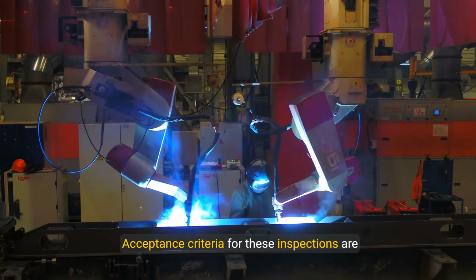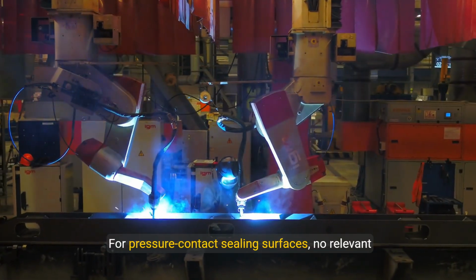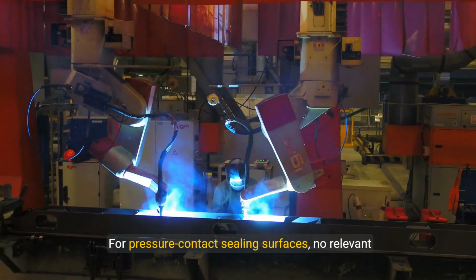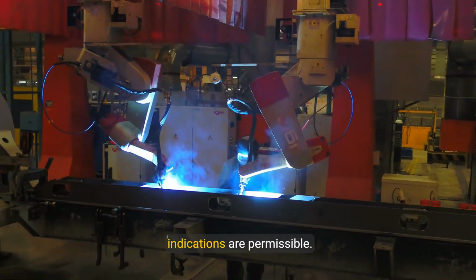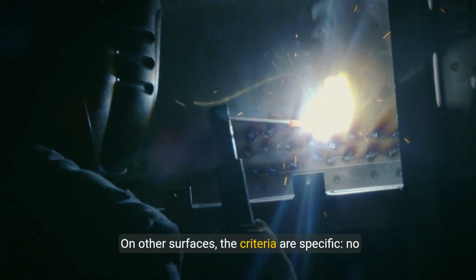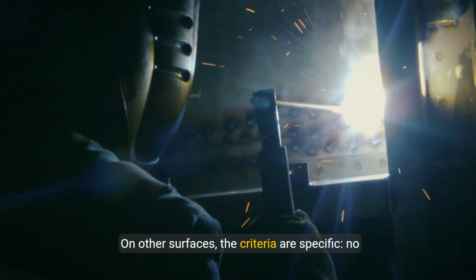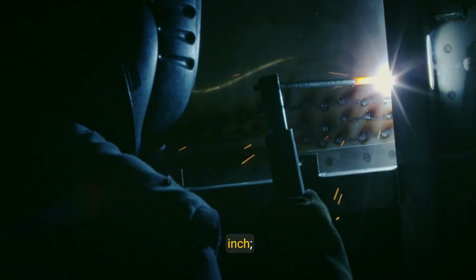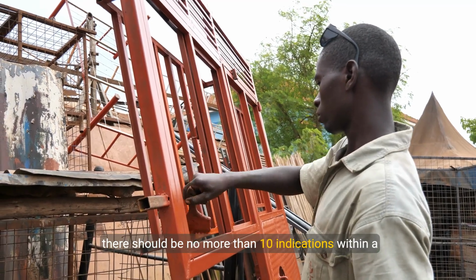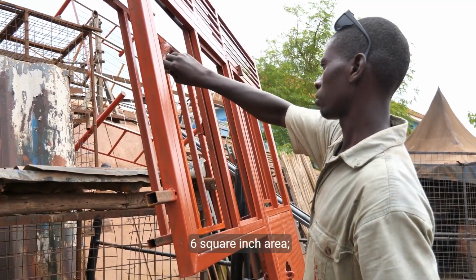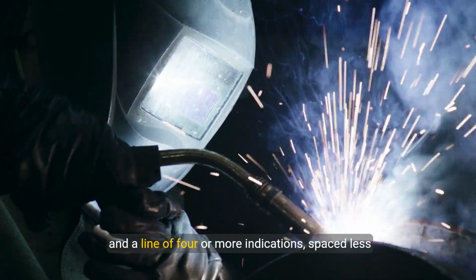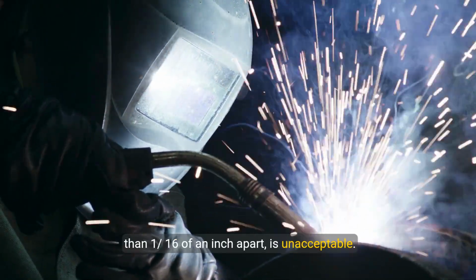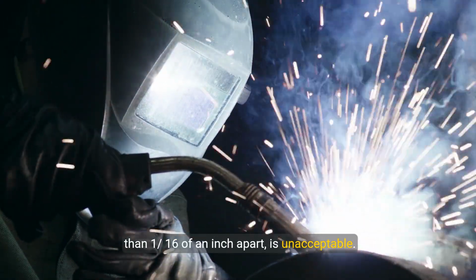Acceptance criteria for these inspections are stringent. For pressure contact sealing surfaces, no relevant indications are permissible. On other surfaces, the criteria are specific. No indication should be equal to or exceed 3/16 of an inch. There should be no more than 10 indications within a 6 square inch area, and a line of 4 or more indications spaced less than 1/16 of an inch apart is unacceptable.